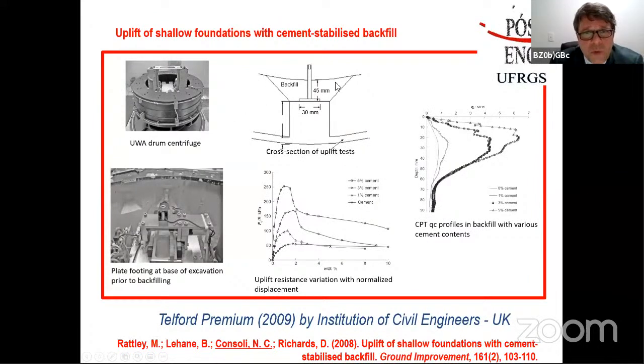We can observe that in this case, the backfill was filled with cement, 1%, 3%, and 5% of cement, or without any cement. And then we have pulled it out after some period of curing, and we can observe in this case here the results, this is a normalized force that was observed to pull out this shallow footing that we have here, without any cement.